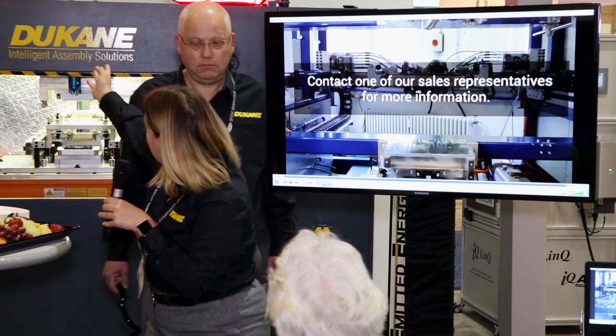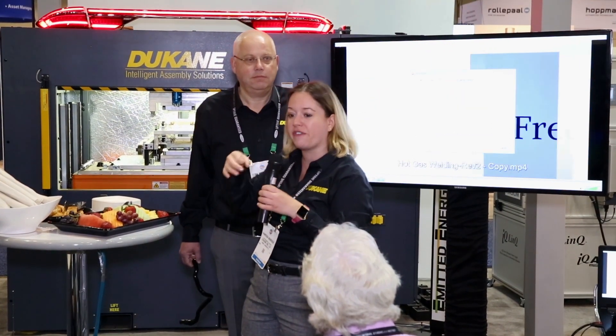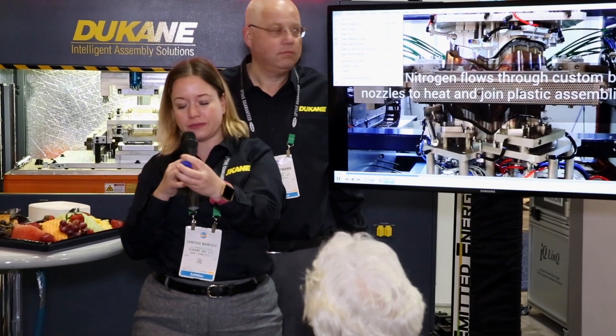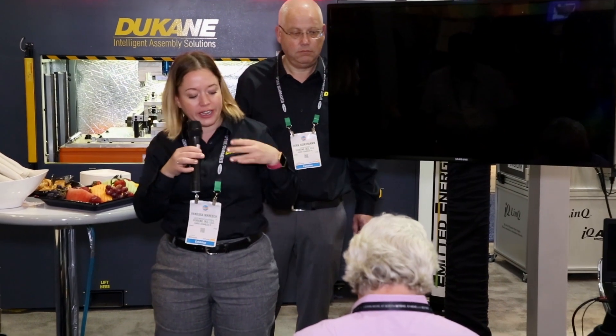The rear lamp at the back, for example, is also welded with hot gas welding. So it's no problem to weld if you have electronic parts inside, or if you have a valve or something near to the weld bead. We have a hot gas welded sample part here — you can take a look. We have made tests: you have absolutely no mechanical stress on the weld bead, because we heated up the part without touching it, and after it plasticizes the part, we join it. So it's a very smooth process and absolutely stress-free for the part.